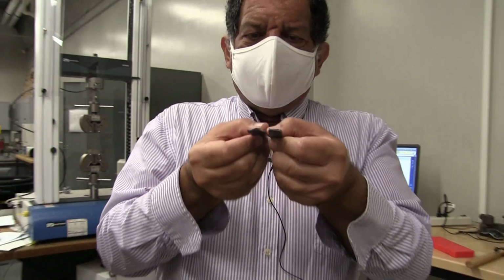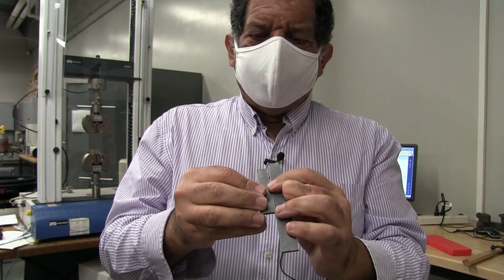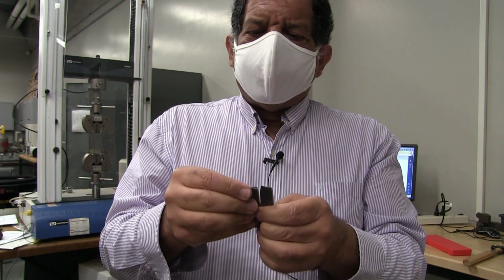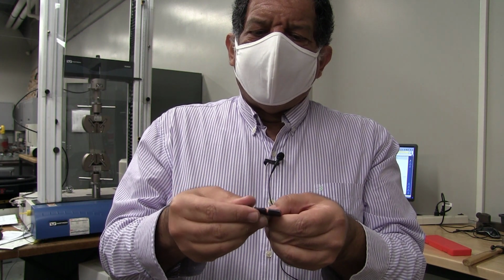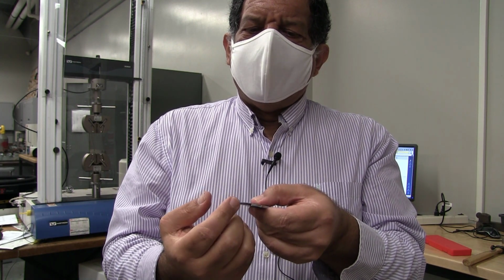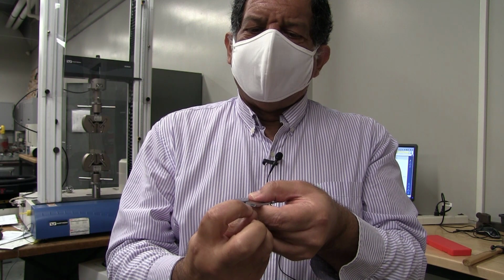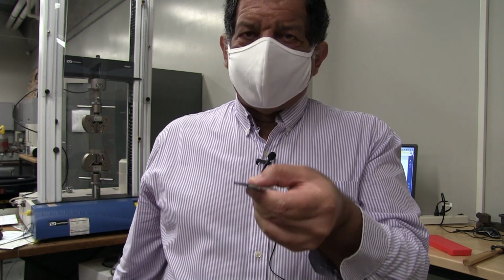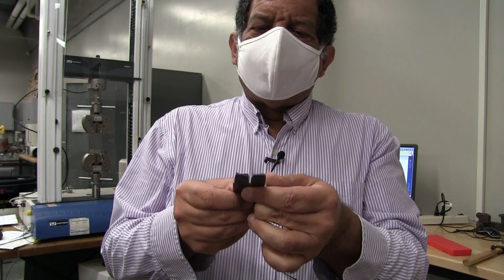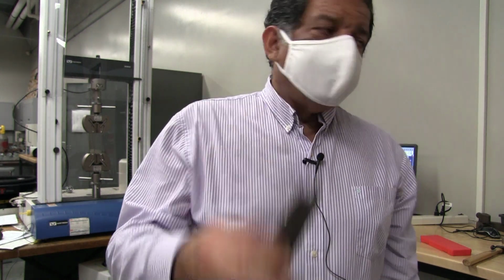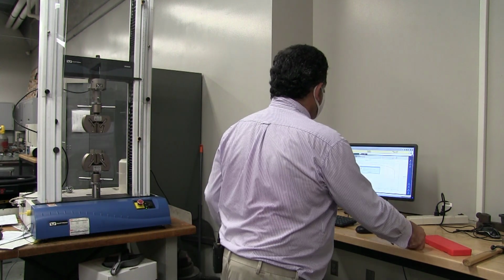And it's really kind of cool to take a look inside there too. So I don't know if you remember from your ME 3150, the fact that there's shear lips over there, and then there's void nucleation and growth on the inside of the fracture. It's pretty cool to look at a ductile fracture surface. Okay, so that's the steel specimen.